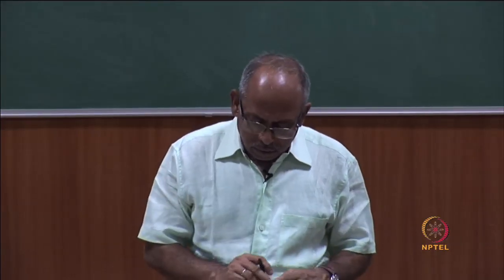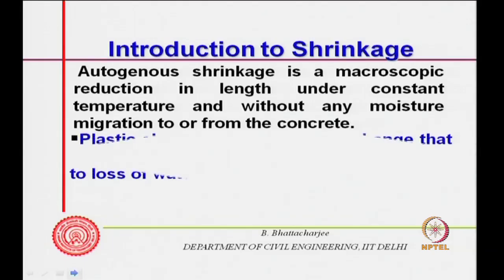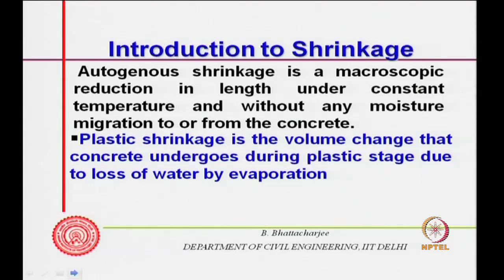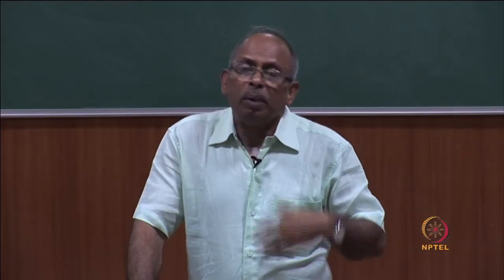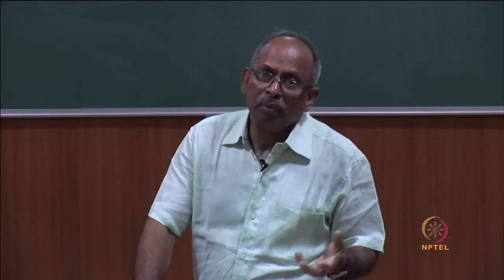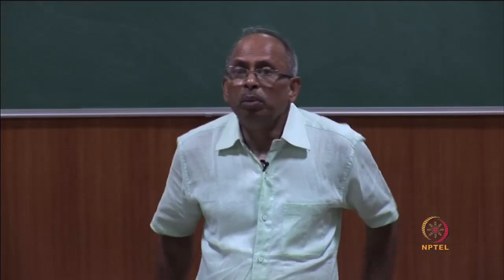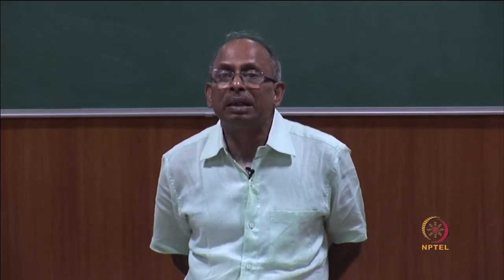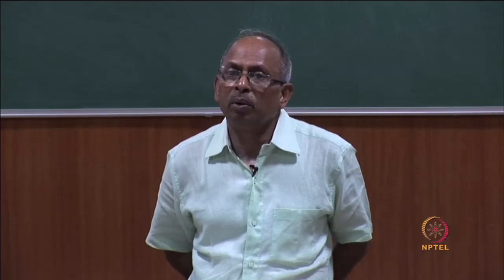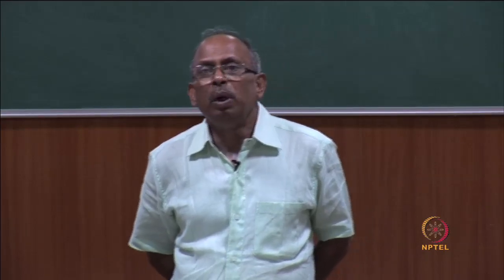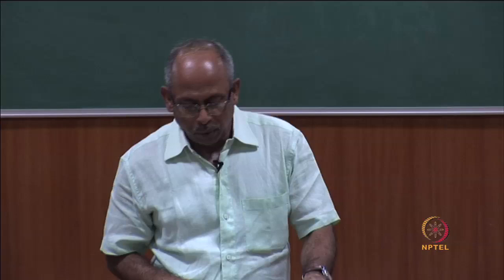So, this is autogeneous shrinkage and chemical shrinkage, and plastic shrinkage is also a terminology used quite often. From a practical and understanding point of view, chemical and autogeneous shrinkage are very useful. But from a practical point of view, the volume change that is occurring during the plastic stage is the plastic shrinkage. So, it is the volume change that concrete undergoes during the plastic stage, and usually that could be due to loss of water by evaporation.